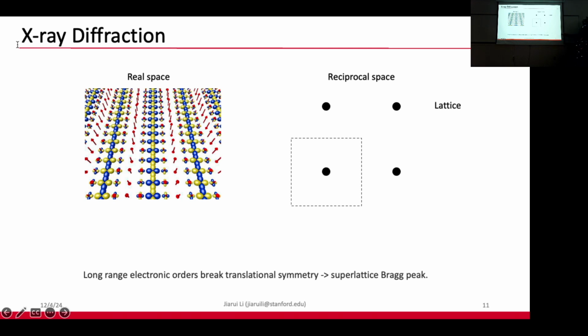If we have a microscopic electronic structure like this, and they are periodically arranged, one of the natural thoughts to measure them is diffraction. And indeed we can do diffraction, but all of these electrons are sitting on top of the atoms, and if you do diffraction, the first thing you see is the lattice Bragg peak, as you see in these black dots. But this extra electronic modulation breaks the translation symmetry of the lattice. For example, the lattice is translationally invariant after each one translation, but these charge modulations are repeating every 4th unit cell. Therefore, you would expect an additional charge superlattice Bragg peak at a quarter away